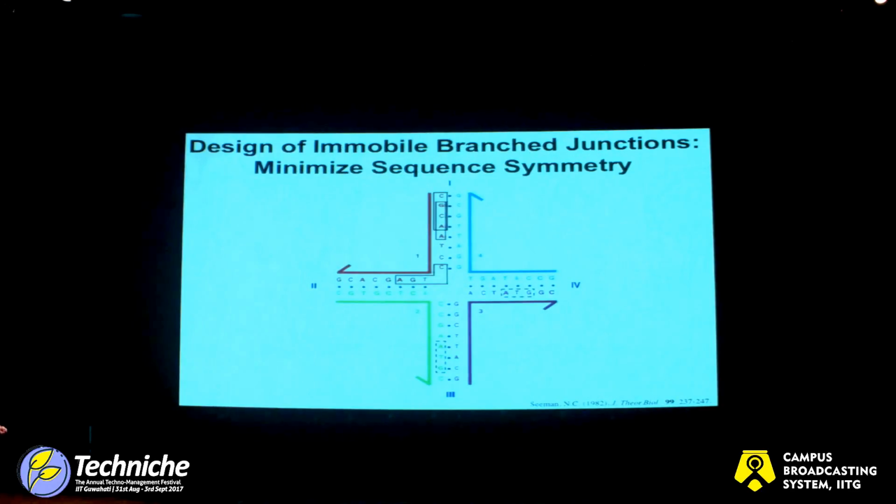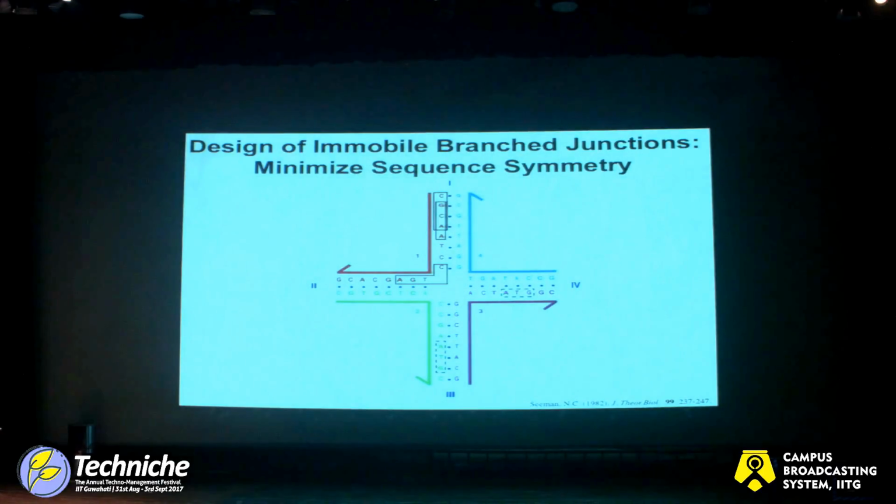Now, it's easiest to look at this system when we draw it like this. So it looks like we have an intersection in a highway. So these are 16-mers of DNA, 4 different strands, 1, 2, 3, and 4. And we've designed the sequences here so that they come together to form this single molecule. I'm not going to go into the details of the design. I'll just say we can do it, and it's rather easy to do. So now we've got a branched molecule. This is analogous to an intermediate in the process of genetic recombination.